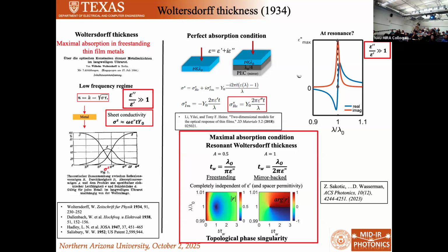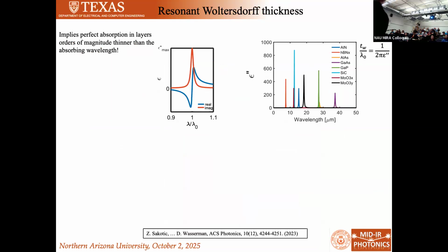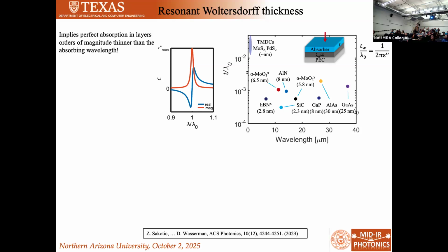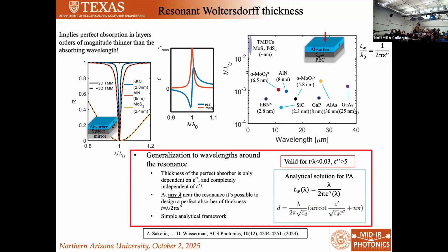And one of the things you notice is that it actually doesn't depend on the real part of the permittivity. It only depends on the imaginary part of the permittivity, right? And so if you have a material with a strong absorption resonance, let's say a phononic material, like any one of these polar semiconductors, which have very strong epsilon double prime at these long wavelengths, you can make a thin film that absorbs all of the incident light that is, in some cases, only nanometers thick. So this is on the order of 10 microns, and you can absorb every single photon in a thickness of 6.5 nanometers, right?